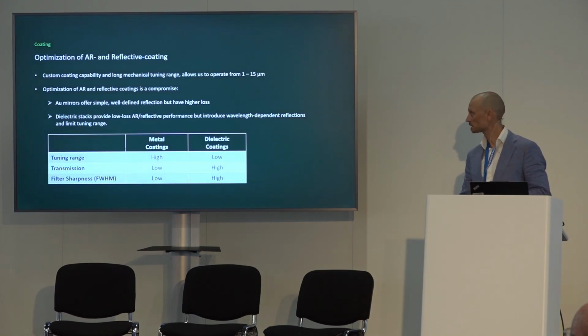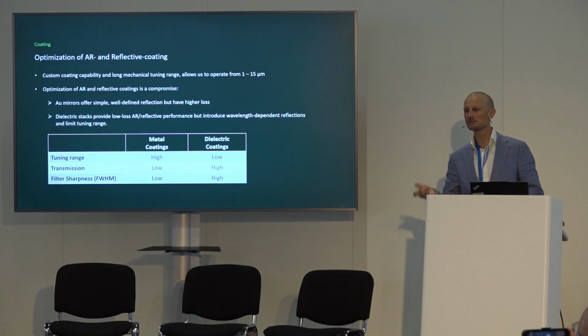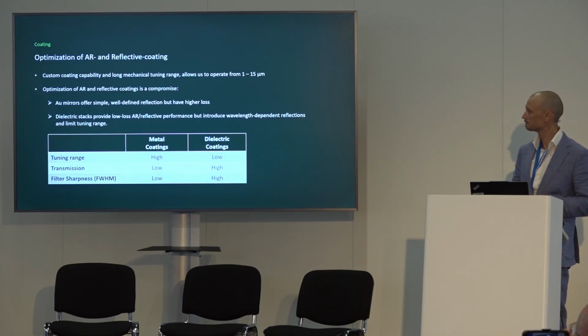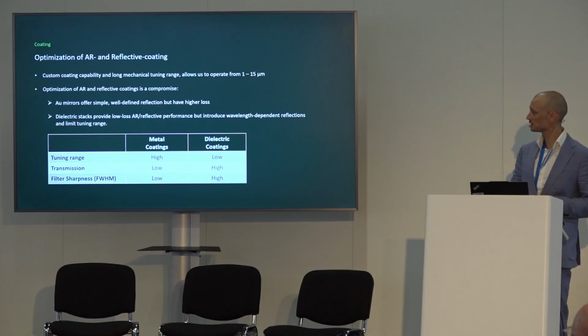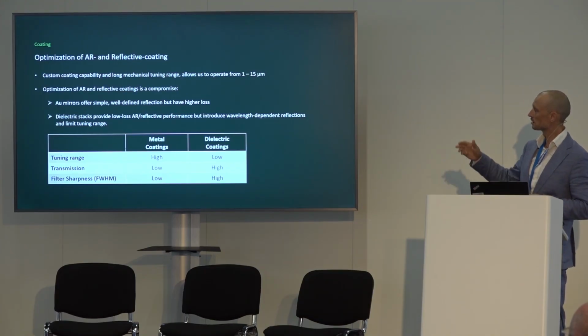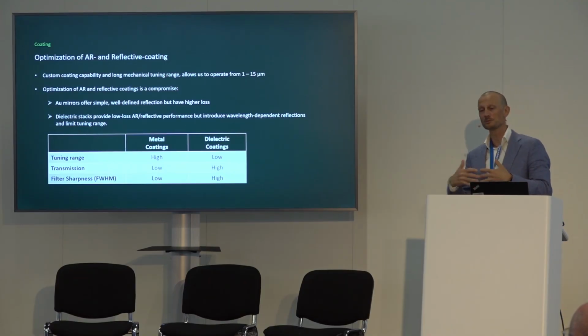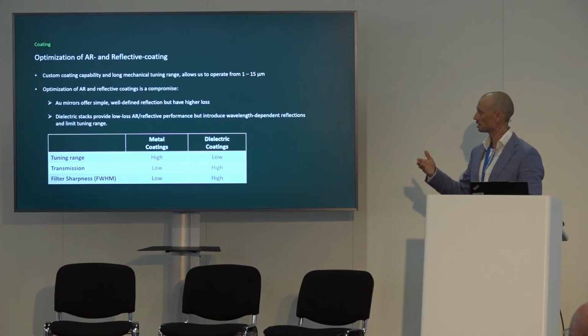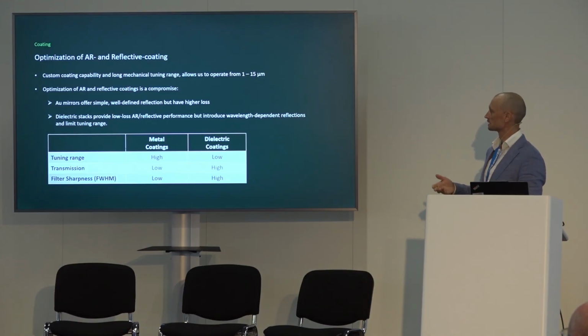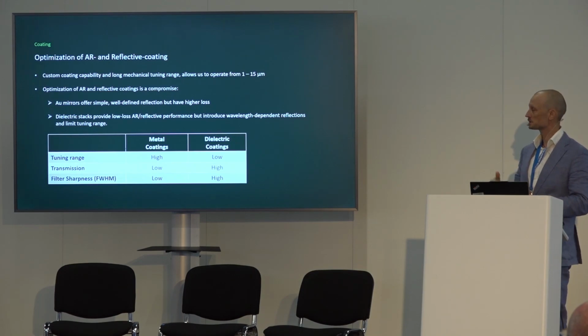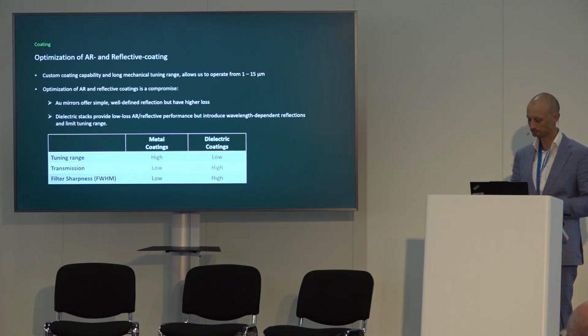And to do that, we naturally need the deep thin film expertise. So we have invested in advanced coating equipment, and have experts in the field working for us. So we can tune the coatings in order for it to match the customer needs. For example, for a high tuning range, you can use metal coatings. In that case, you would typically have the low transmission like you saw in the material example that I showed. Or if you need high transmission, you would go to the dielectric coatings and then maybe compromise on the tuning range. But we can at least play around here with some degrees of freedom.